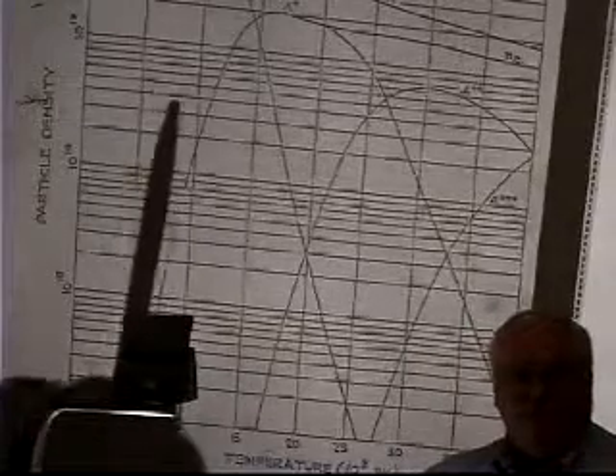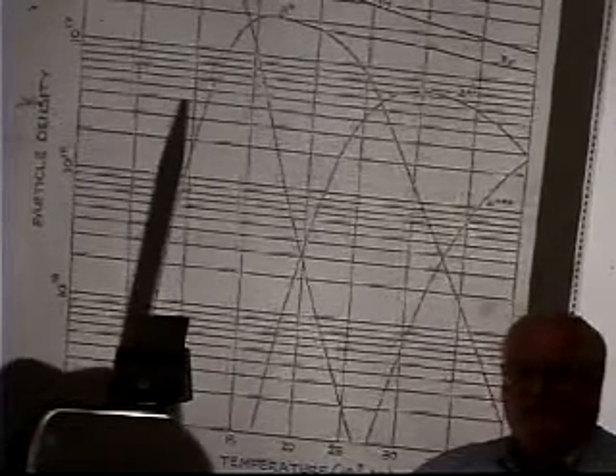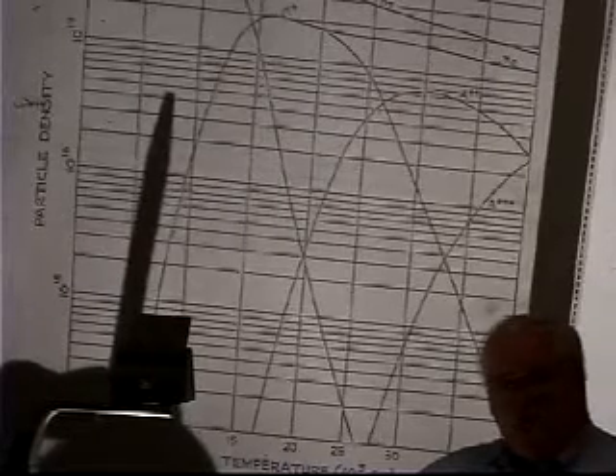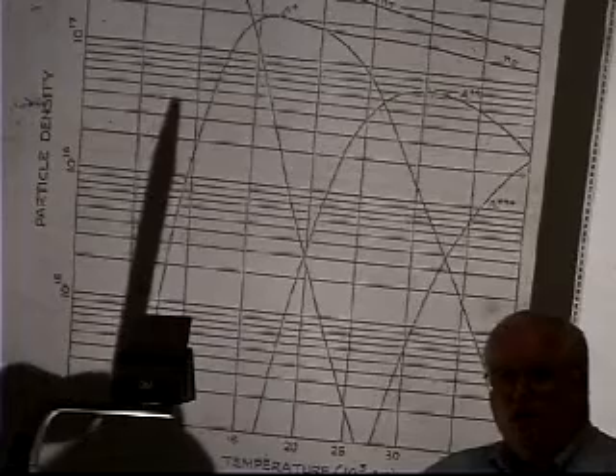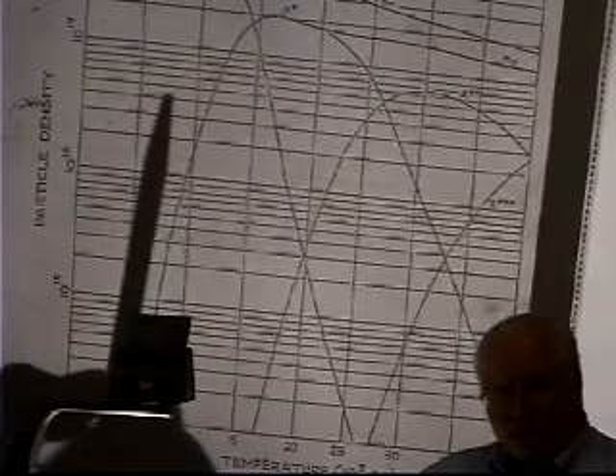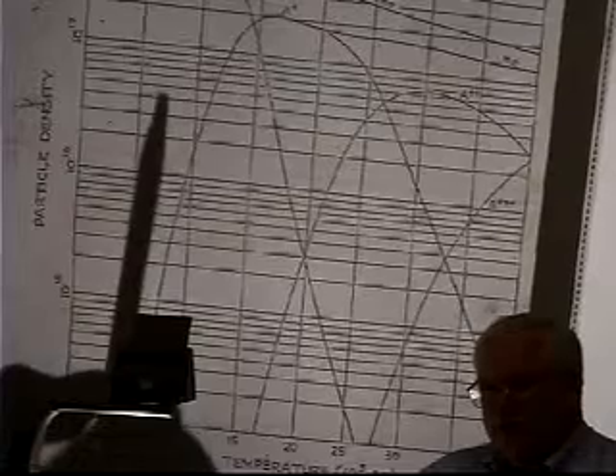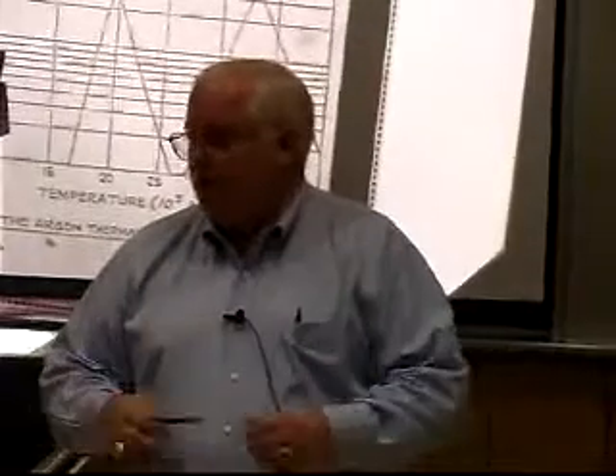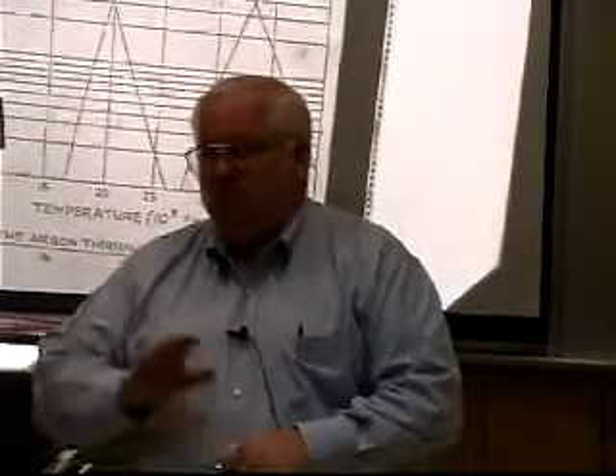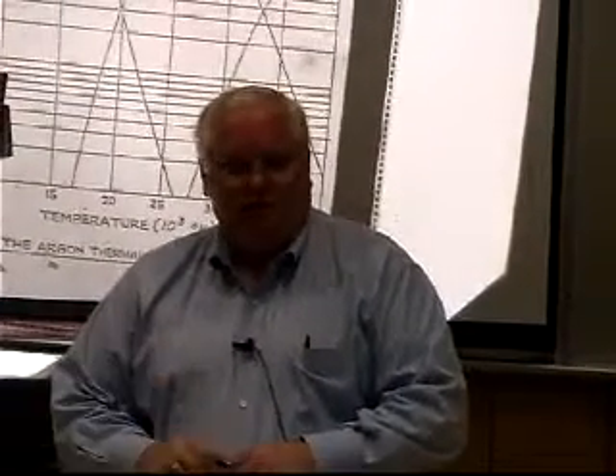So a helium arc, this point where you get 5 to 30% ionized, is not going to be 12,000 degrees, it might be 18,000 degrees. So if I have a piece of water-cooled copper and I strike a pure argon arc, I'll get 12,000 degrees as kind of an average arc temperature. If I strike a pure helium arc, I'll get 18,000 degrees. And people for years have said, well, that's the reason that helium produces a hotter arc and more efficient melting in welding. No, sorry, not right.